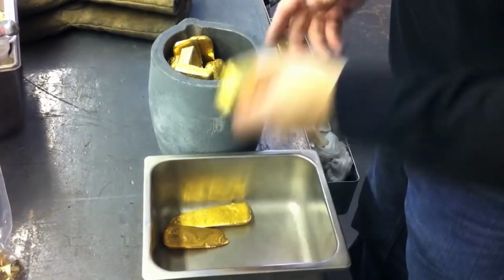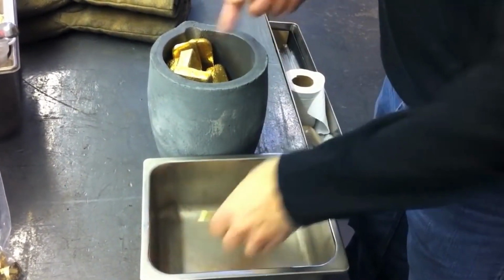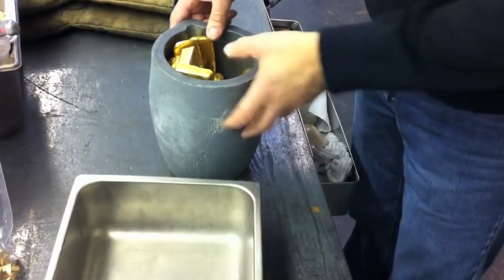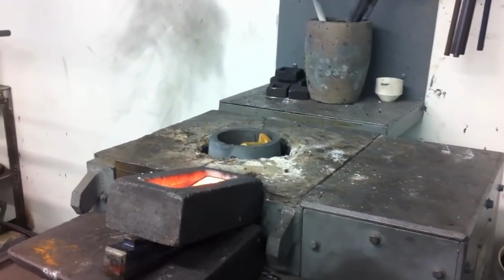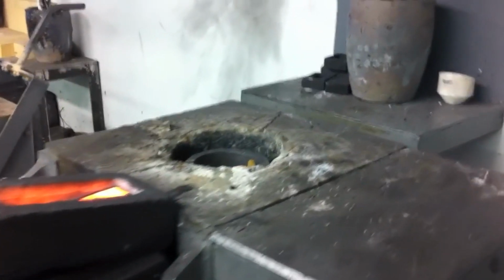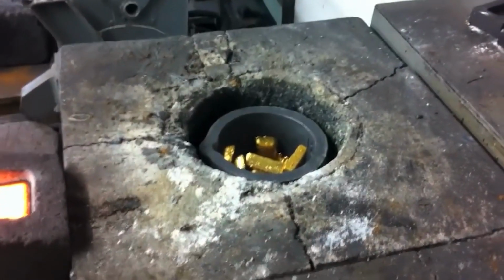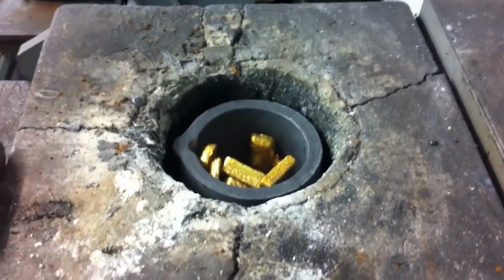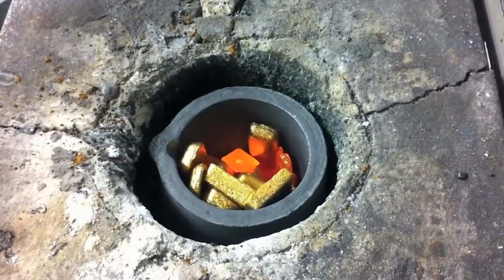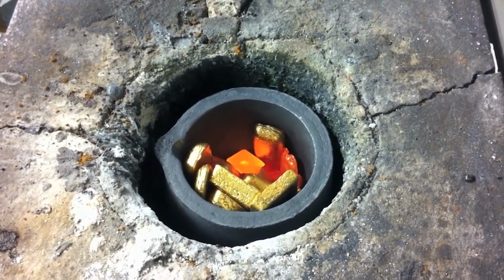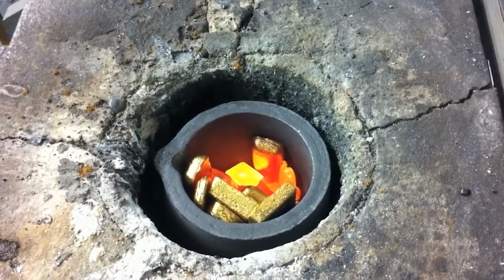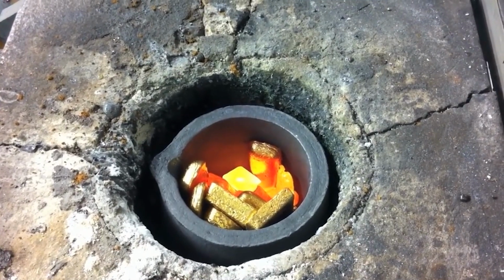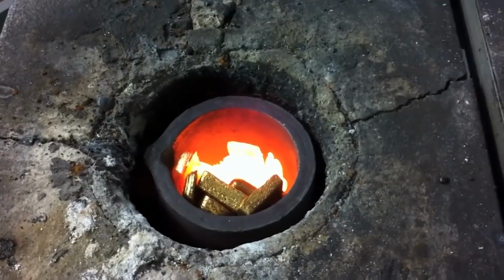Sodium carbonate is an alkaline flux, whose melting point is 850 degrees Celsius, and it reacts with the silica forming sodium silicate. The latter reacts with oxides and produces other oxidized compounds. Sodium carbonate must be added with caution because excessive addition creates sticky slags that are difficult to remove. Fluorspar modifies slag viscosity because it modifies the silicate formed during the smelting process. An excessive addition attacks the crucible and reduces the action of borax and metallic oxides.